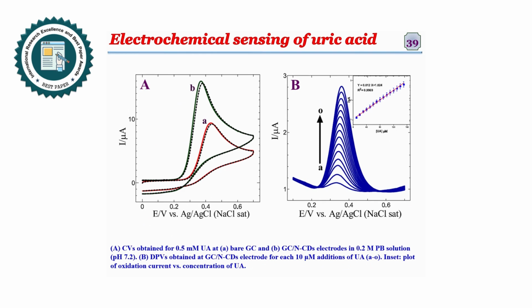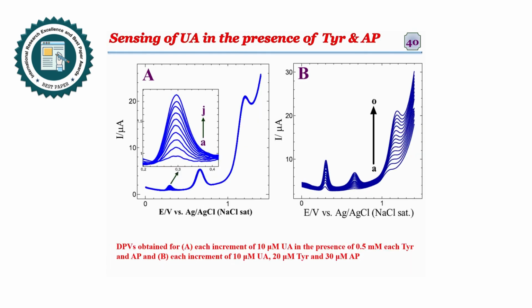And this is the electrochemical oxidation of uric acid. A is at the bare electrode, B is at the nitrogen doped carbon dots fabricated electrode. So when compared to the bare electrode, the NCDs fabricated electrode exhibited higher electrocatalytic activity towards the oxidation of uric acid, and we can detect uric acid at different concentrations, each additional 10 micromolar.